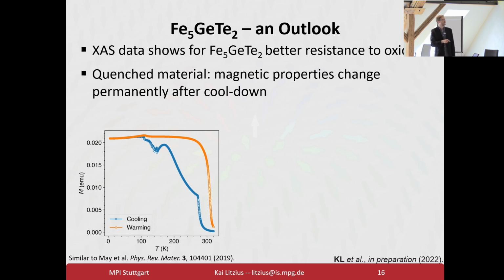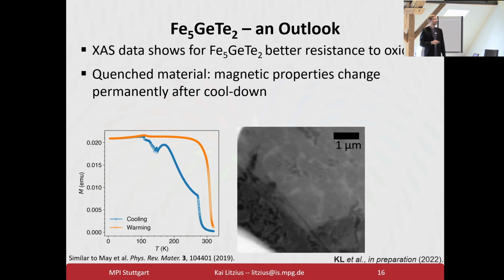And this different loop, once you reach room temperature and you go back, will be the permanently stable phase afterwards. So something has happened in the flake. There's a morphological change that's happening in the flake, and that changes the way the magnetization reacts inside. So we wanted to have a look at that in STXM and see what's actually happening in the flake. And if you look in the flake, I hope it's visible, the contrast isn't really great, you see veins of different iron content. So the quenching of the material freezes in different iron areas, which means that this material is very inhomogeneous and not really suitable for, for example, racetrack or reservoir or whatever applications.